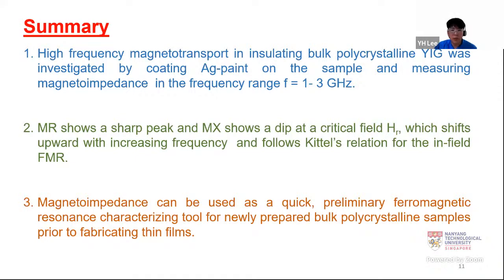in insulating bulk polycrystalline YIG sample was investigated, just using the silver paint on the sample, measuring the magnetoimpedance in the frequency range of 1 to 3 gigahertz. The MR shows a sharp peak, and the MX shows a dip in the critical field regions, and it shifts to the higher field with increasing frequency. One thing we would like to highlight here is that it actually follows the Kittel relation for the in-field FMR.